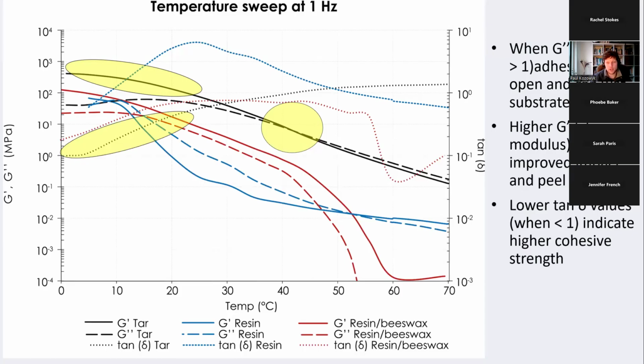And lastly, when the elastic portion of the material is dominant, so when the adhesive is set, a lower tan delta value, or this is a ratio between G prime and G double prime, generally indicates higher cohesive strength, so the ability for the adhesive to stay together within itself. And again, this is good. You want a high cohesive strength in an adhesive. And for birch bark tar, this is better than the other two mixtures. What it's being compared to here is a pure resin and also a resin and beeswax mixture, because the pure resin on its own is really not very good. And there's some evidence that it was mixed with beeswax to try and improve that. So that's what we're comparing here: tar with the resin and beeswax.